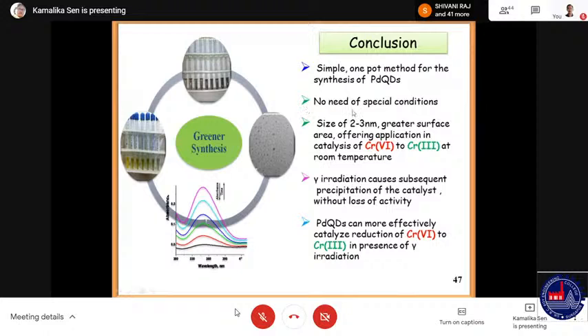So this is the conclusion that 2 to 3 nanometer particles have been attained, which can reduce chromium-6 to chromium-3, and these are more effective when done in presence of gamma irradiation.